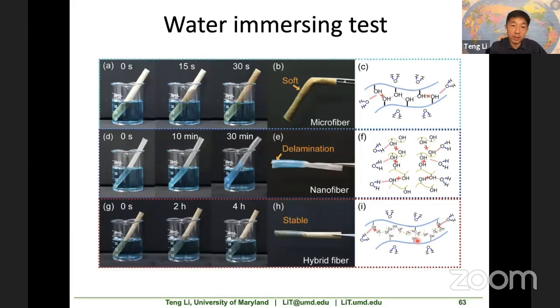Now, what about the water stability? So this is a pure microfiber straw. In 30 seconds dipped into water, it becomes soft. It's not working. And if you have a pure nanofiber straw, it remains stable in water for 30 minutes, but it causes delamination. Now, if you mix these two together and make this hybrid fiber straw, you can immerse it in water for 4 hours, and it doesn't cause delamination and it remains stable.